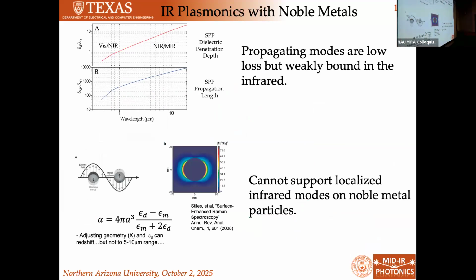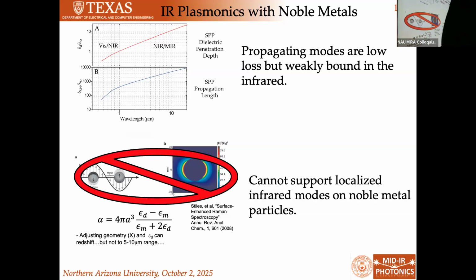And there's some real implications of using noble metals. If I look at, for instance, the penetration depth, in other words, how tightly I can confine this mode, and the propagation length, what you'll see is that as I move to these long wavelengths, my penetration depth gets very large. In other words, my mode extends for 10 wavelengths, for instance, beyond the metal. So that is not sub-wavelength confinement, obviously. That's 10 times the wavelength. This is not really a plasmonic mode in any sense of the word. This is just a surface wave on a metal. Now, the advantage is, of course, that it propagates for a very long distance, but that's because it's loosely bound. It's not really exciting the charges in your metal. This is not really plasmonics. And again, if you're looking for the resonance associated with the localized mode, you can't hit it because your metal permittivity is too large.